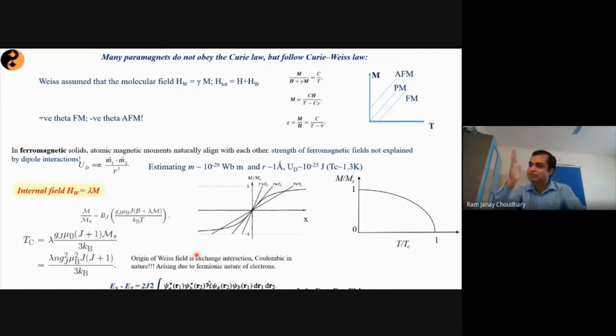All these materials are paramagnetic beyond a critical temperature. That critical temperature can be the Curie temperature or the Neel temperature. Beyond that temperature, there is no exchange force acting between those electrons to keep them aligned, because thermal energy has overcome the exchange energy and all those electrons have become paramagnetic. Only below that particular temperature, where thermal energy is lower than the exchange energy, does magnetic ordering take place. Either it becomes a ferromagnet or an antiferromagnet. These are the examples of ferromagnetic cases which I have.